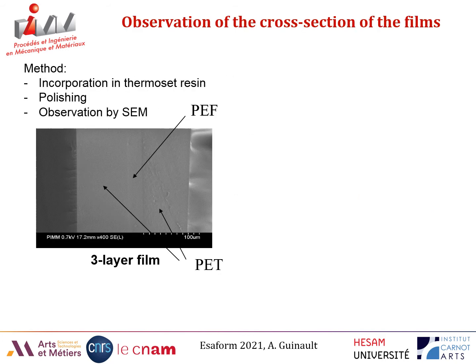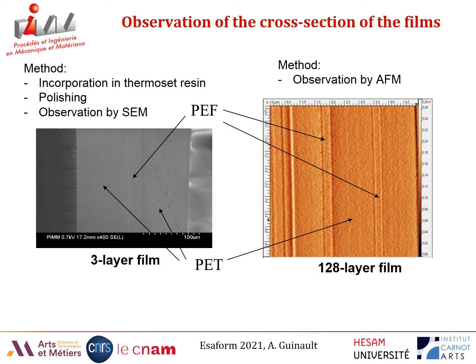Now we have observed the morphology of PEF in the film. In the 3-layer film, you can see on the figure that you have a continuous layer of PEF inside PET layers that are outside. For the 128-layer film, you can see the PEF layer and the PET layer clearly.